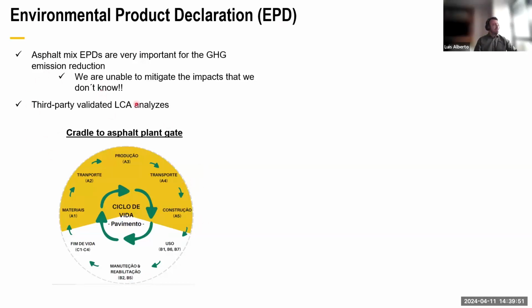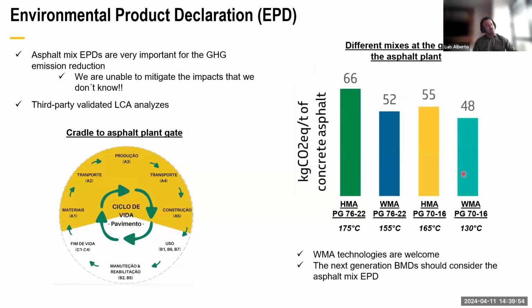So here we have some third-party validated LCA analysis, and I brought some examples that you need to think about. These are some carbon footprints of some hot mix asphalt and warm mix asphalt. They came from the same asphalt plant. Here we have a hot mix asphalt with conventional binder, a PG 70-16, and here we have a polymer modified binder with PG 76-22. So we can see that in both cases, warm mix asphalt technology could reduce a lot the carbon footprint of the asphalt mix.